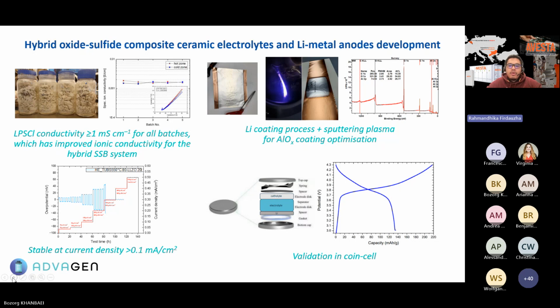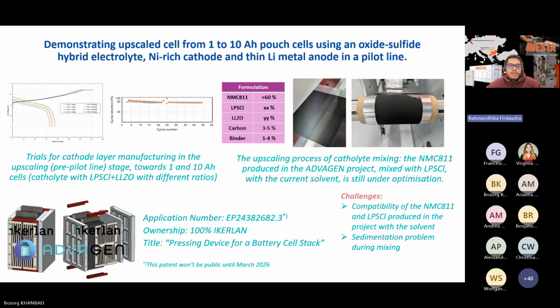And validation for all of them, like NMC 811 of Advagen, LPSCL, and LLZO hybrid, and then with the lithium metal, is also validated in a coin cell. Even though the capacity dropped a little bit from the original NMC 811 capacity, it can be categorized as a successful trial. And then for the next, demonstrating upscaled cells from 1 to 10 ampere hour pouch cell using an oxide sulfide hybrid electrolyte, nickel-rich cathode, and thin lithium metal in the pilot line.